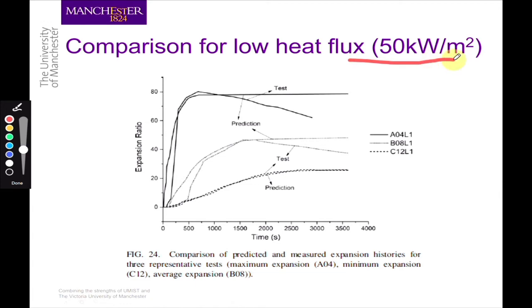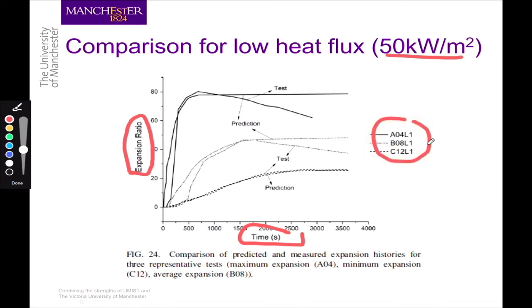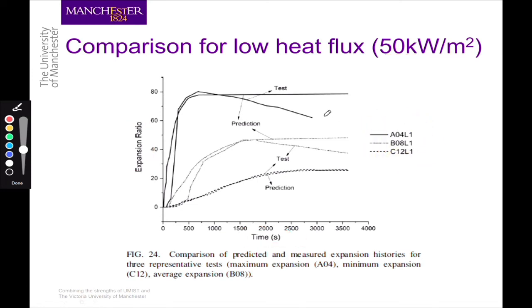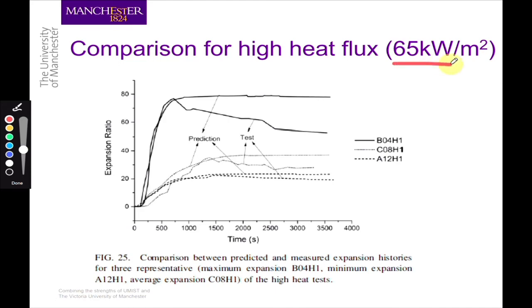under different heating rates. This is so-called cone calorimeter heating. So we predict expansion ratio as a function of time under this heating rate for different thicknesses of steel and the coating. And you can see in here the results are quite good. So that's our test. These are predictions. There is, of course, this stage of reduction in expansion that's caused by oxidation, which can be relatively easily dealt with. That is done under different heating levels. Again, the results are quite good.